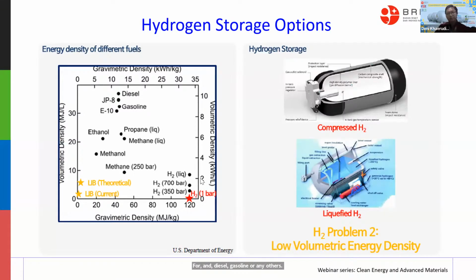If we want to increase the volumetric density, it should be compressed. When compressed using 350 bar, it increased a little, and at 700 bar a little higher, and the liquid is even higher. But when compared with methane and methanol, the volumetric density is still lower. But again, in terms of the gravimetric, hydrogen is superior.